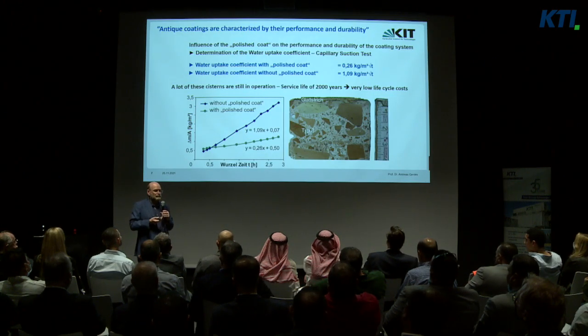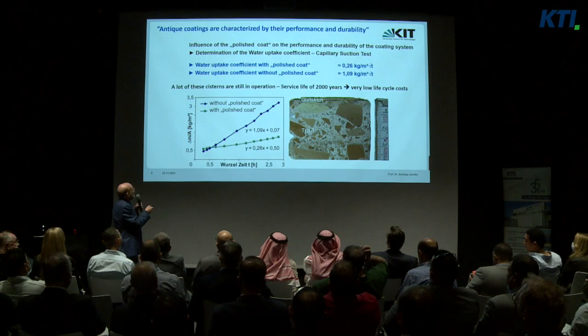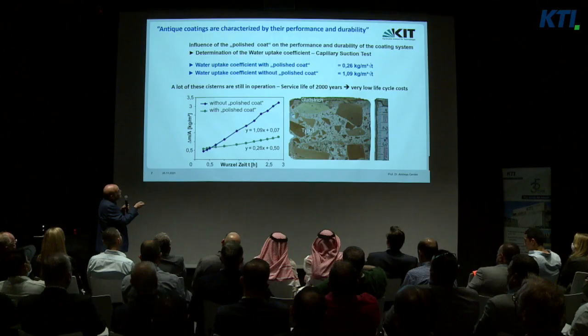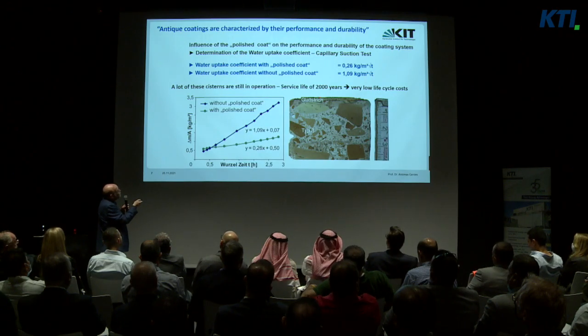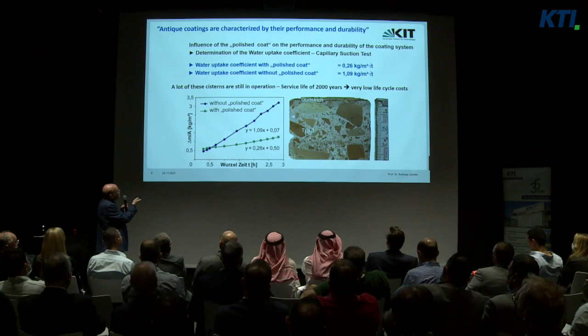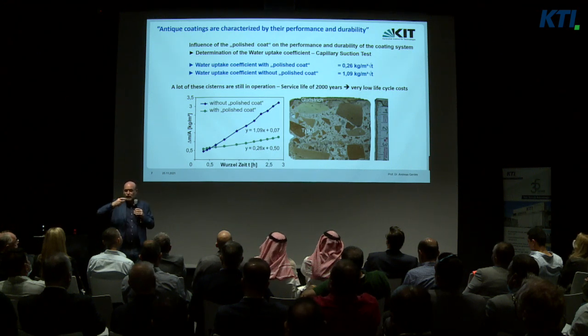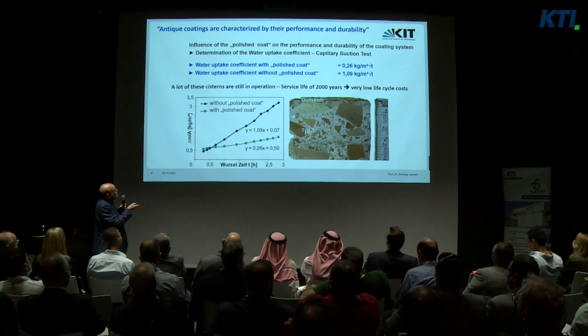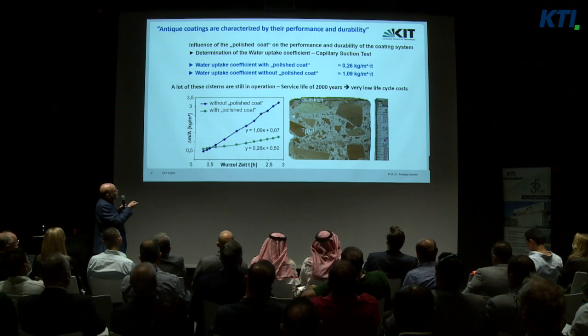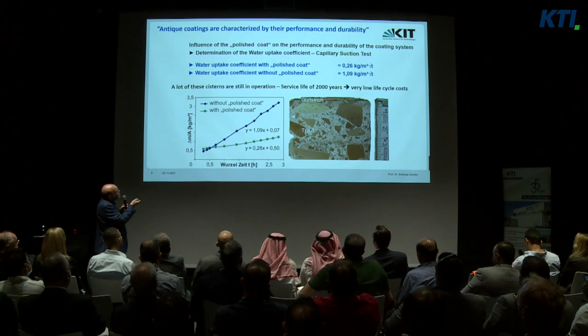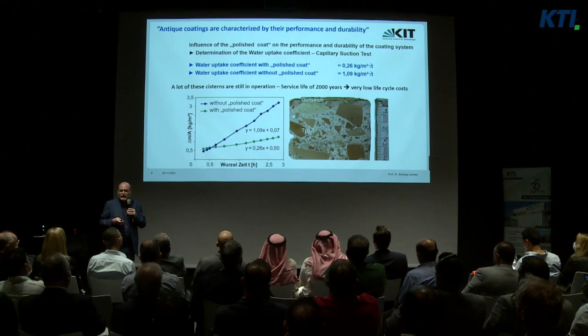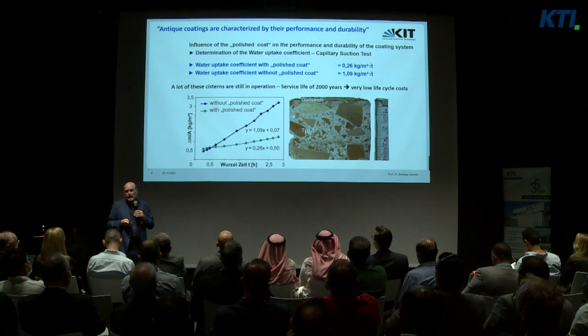Because if you have a new cement-based material like a mortar or concrete, you will have this layer or this part of our concrete be porous, so we have there a high water uptake, and the rest of the concrete will have a low water uptake. So it's quite the opposite compared to the old system. But this is the reason for the high durability, because due to the dense pore structure, there's only a low transport of calcium out into the drinking water, and what is lost can be transported in the covercrete, and therefore we can stabilize this very thin layer, and that leads to the high durability.